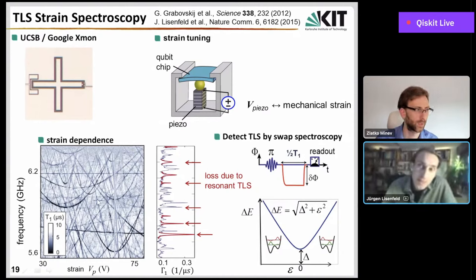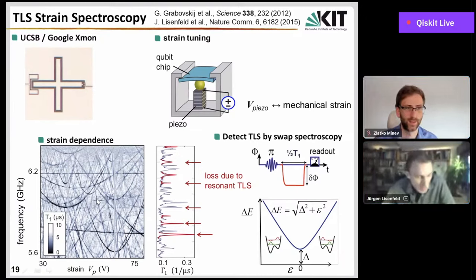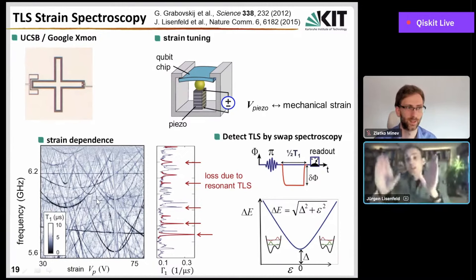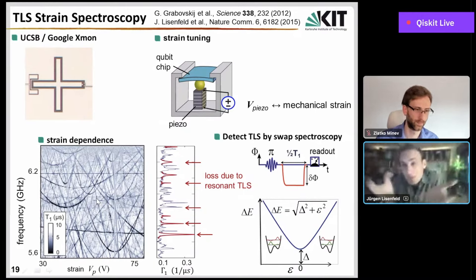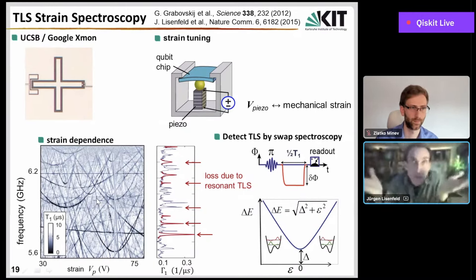Are there competing theories on what could explain this other than TLSs? As I said, in general, this standard tunneling model based on the double-well potential works without a microscopic model of this defect. So as long as you have this double-well potential, which is very likely to have for various kinds of defect implementations, then you would get these hyperbolas basically.